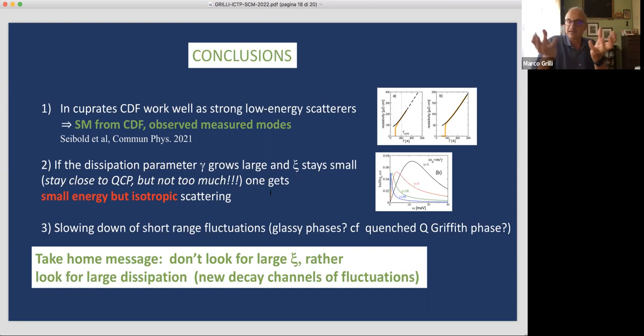And we can adjust this bottleneck, and we can avoid this bottleneck, having at the same time a small energy for the scatterer and still an isotropic scattering. Okay, now this slowing down of the short range fluctuation is something which can proceed and give rise at zero temperature even to glassy phase.